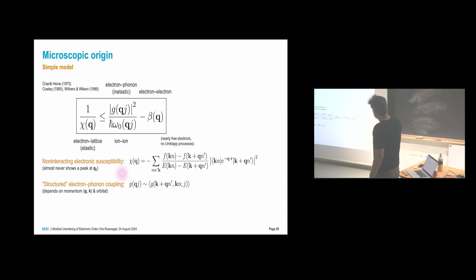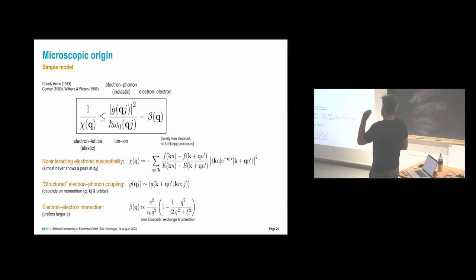Then you have this term, which is really important. It's a structured electron-phonon coupling. So this depends on momenta, the Q of the phonons and the K of the electrons, and it depends on orbital. And then you have this electron interaction also included. So you have four factors that are relevant, and then you can say, okay, obviously to fulfill this equation here, this should be large, so that you have a small number on this side. This should be large because it's up here. This should be small, and this should be small.